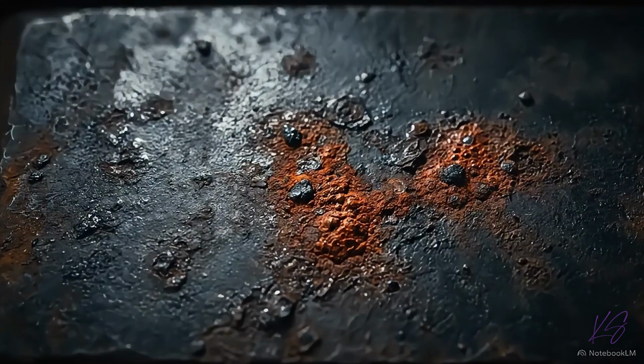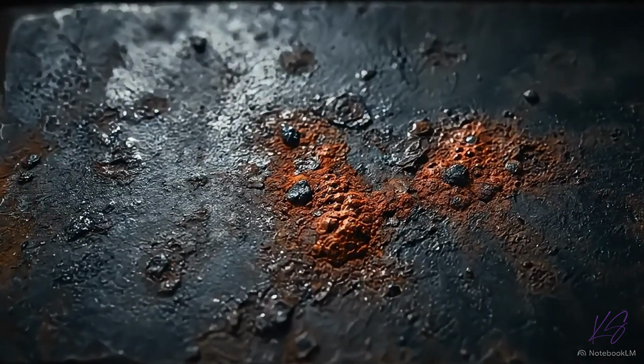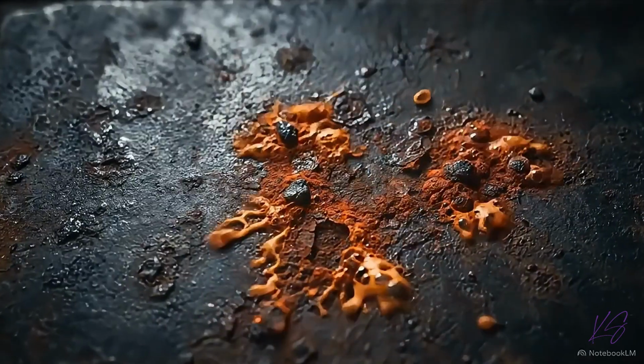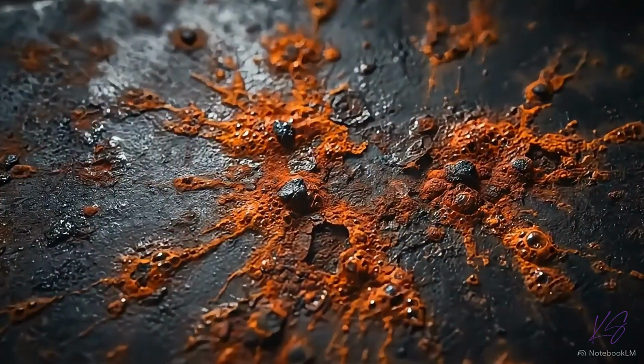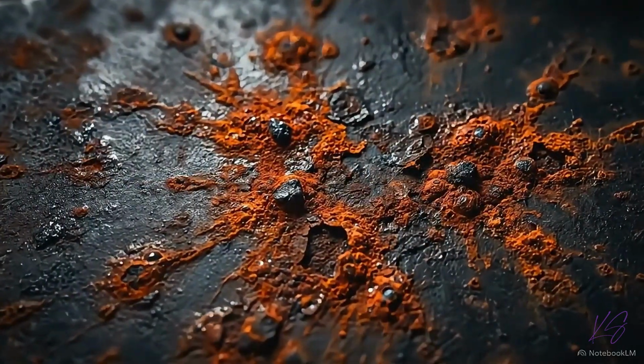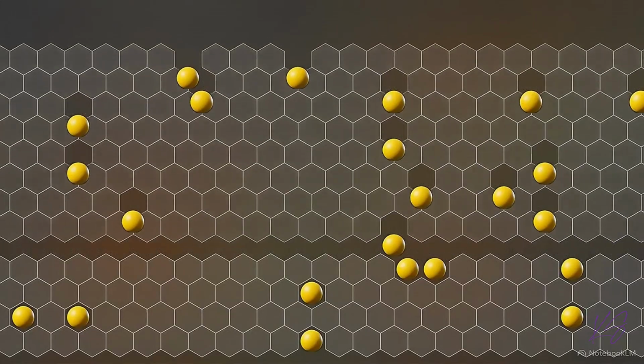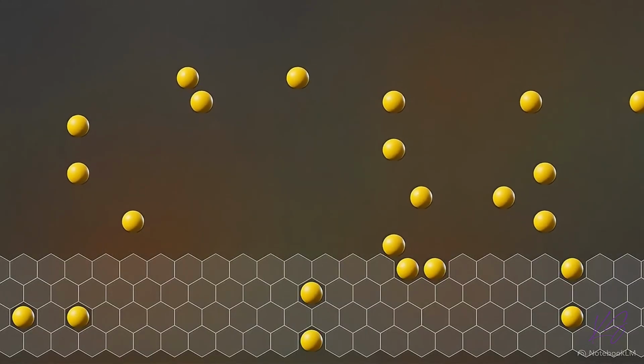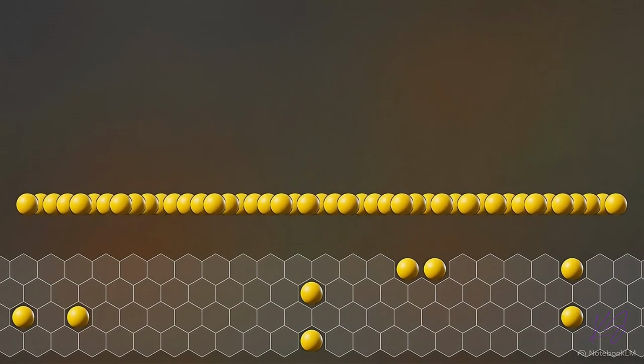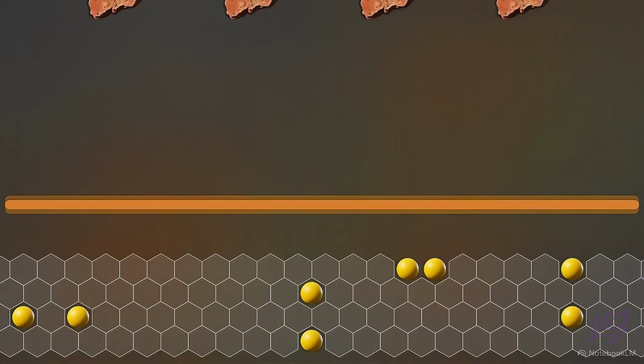When the pillar was first erected, those trapped slag particles accelerated the initial decay, creating intense, localized corrosion across the surface. As the surface iron dissolved, the phosphorus did not wash away. It stayed behind, rapidly concentrating and altering the typical cycle of flaky, porous rust.